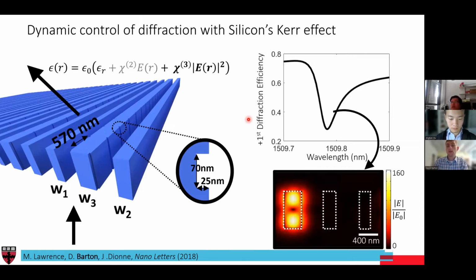And locally, the field intensity is amplified quite a bit. In this case, the maximum is about 160. But on average, the electric field is actually enhanced by about a factor of 100. And so using this chi3 parameter, what this means is that we're able to amplify this Kerr effect by about a factor of 10,000. And so what that means is that if we crank up the power, we can change the permittivity and start playing around with the actual response of this device.